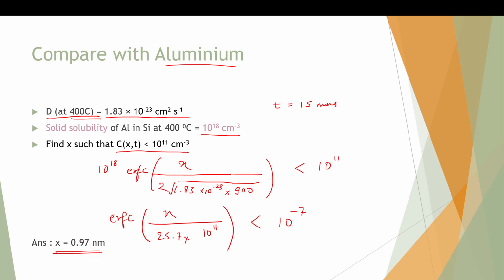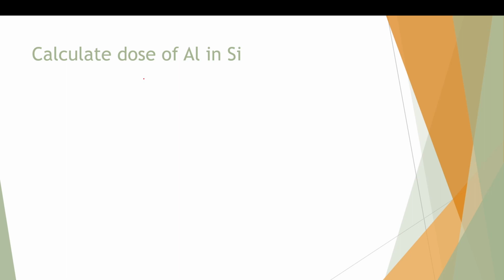Basically, if you find it out, I'm not able to do it right now, but we should get it somewhere around 0.97 nanometers. Similarly, we can also calculate the dose. So the dose equation is Q of T equal to 2 by root pi, Cs root of Dt. So from this we know all the things. We can calculate the dose of aluminium.